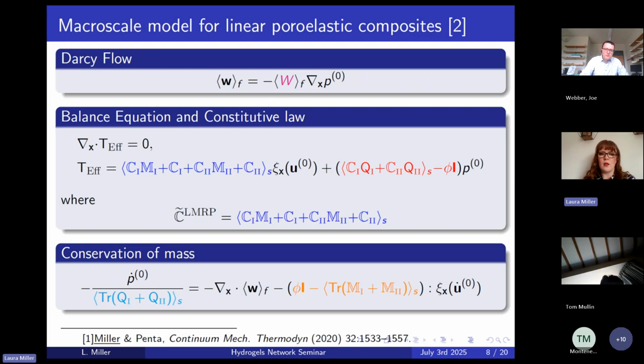We then have a balance equation and our constitutive law. So our balance is just this balance of our effective stress that we've called it here. And this comes in two parts. So we have this fourth rank tensor here that I've highlighted in blue, which is our effective elasticity tensor for our material. And that is what is encoding the fact that we have a difference in the elastic properties at different points in the microstructure. So that is again to be computed by solving some of the microscale cell problems. And it's remembering that we have our ECM and we have our fibre that can have different elastic moduli, so that they can have different Young's modulus, they can have different volumes, the different geometries. That is all being remembered in that tensor.